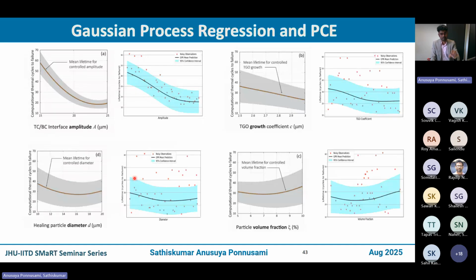A follow up to the second example: what we really did is a toy exercise. We used PCE as a surrogate, but why not use the same data set and train a Gaussian process regression? What we observed is that you basically get the same result. So the question is, do we need to complicate an architecture? Because if we are clear about the requirements, using a simple architecture is more than sufficient. For example, here, use of a CNN is an overkill for sure.